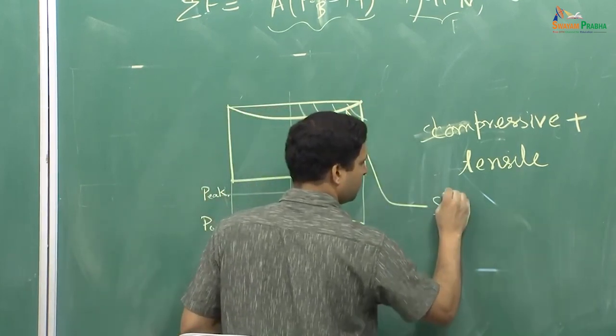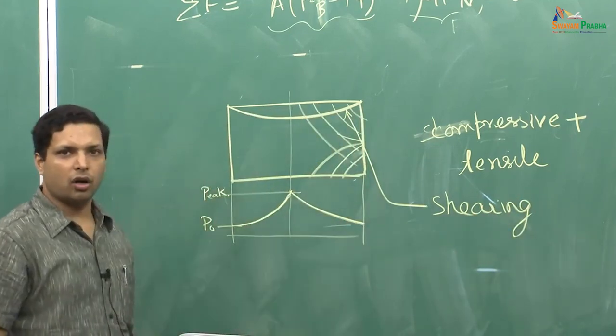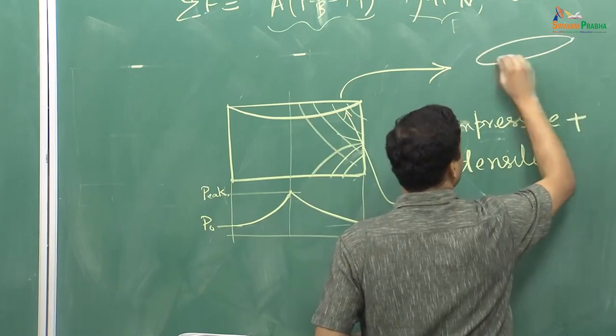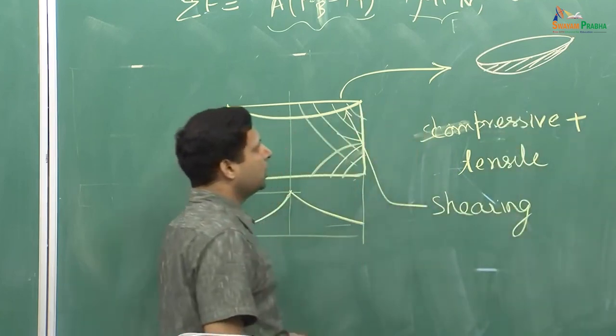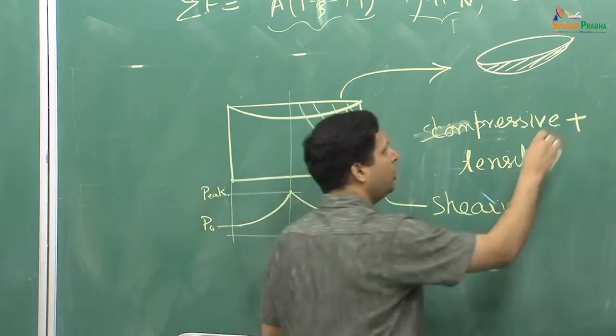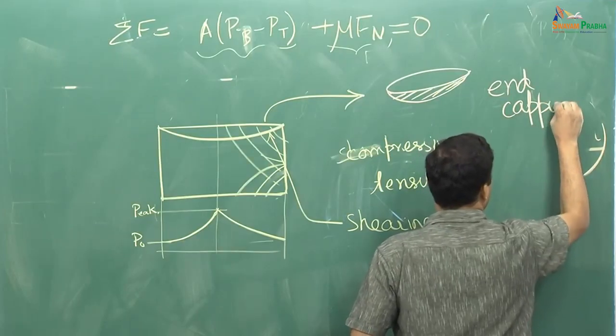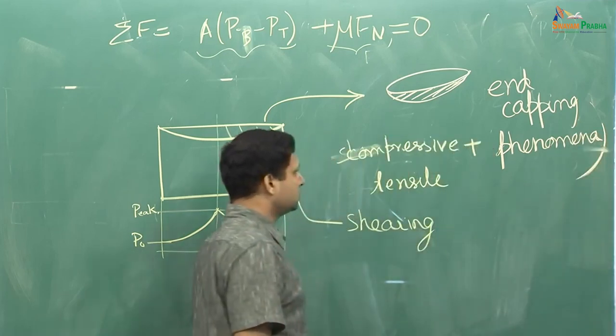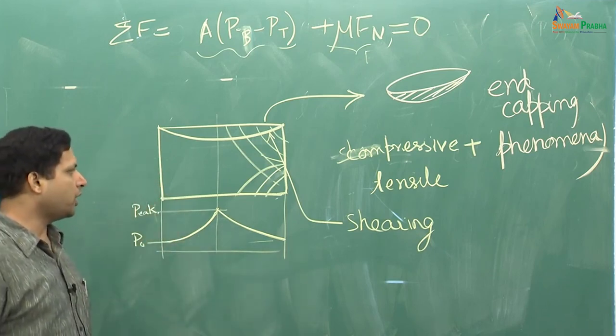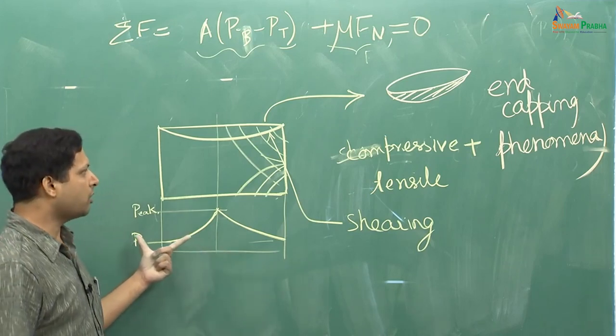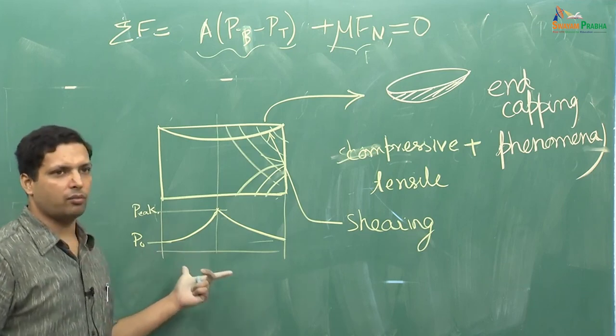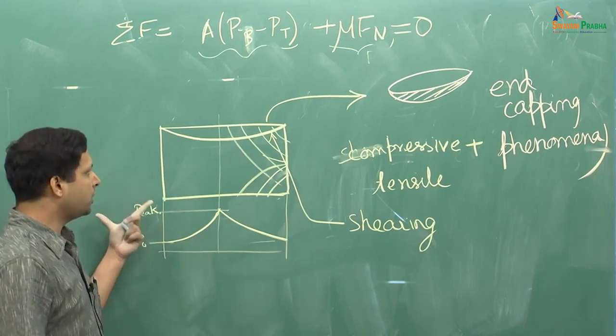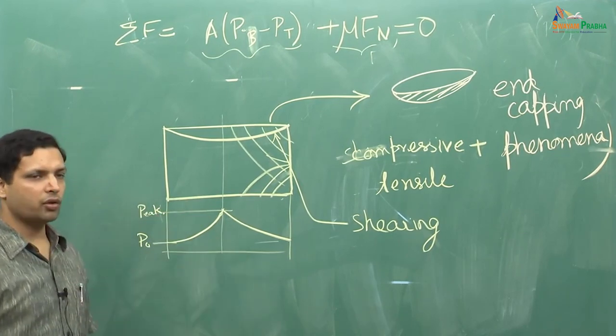A small region just near the top breaks off. As you can see, it is like a cap shape, and that is why it is called the end capping phenomenon. This is also important particularly when you are applying very large forces and large compaction pressures. This is another reason why we should not apply very large compaction pressure — you have to optimize based on the density saturation plot and by finding out when the pressure becomes so large that you start to see end capping.